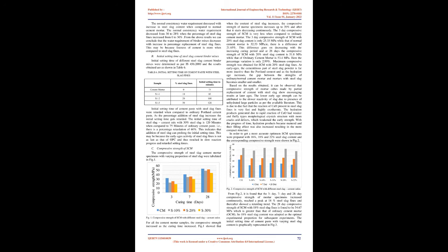Compressive strength, MPa, versus curing time, days, for SCM with 10%, 20% and 30% steel slag. Fig 1. Compressive strength of SCM with different steel slag cement ratios. For all the cement mortar samples, the compressive strength increased as the curing time increased.